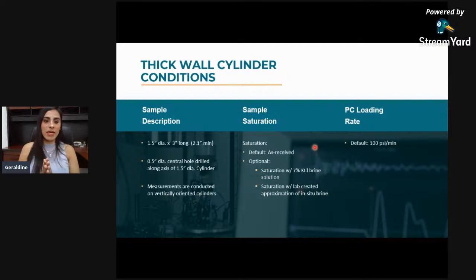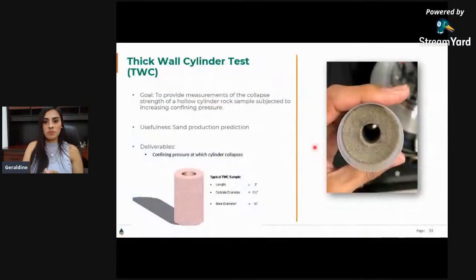The saturation is the same as received or a standard with KCl or any brine solution. The confining pressure loading rate will be, as a standard, 100 psi per minute. In this test, we also want to fail the sample in a short time, in an appropriate time. That's the way this loading rate was determined, by recommendation of the International Society of Rock Mechanics.